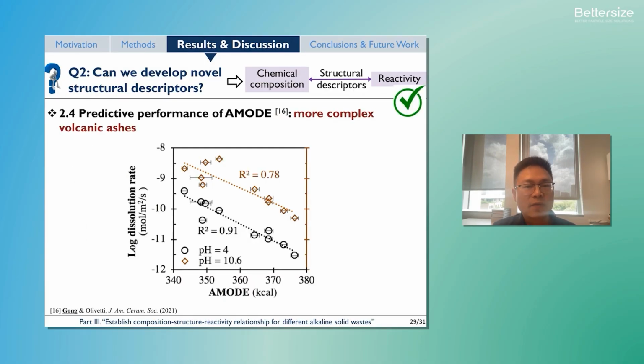Now, here are the results. The lower Amode values mean lower energy required to break the sample, and therefore higher reactivity, and therefore higher dissolution rates. And yes, they are captured, right? So we get these inverse correlations.